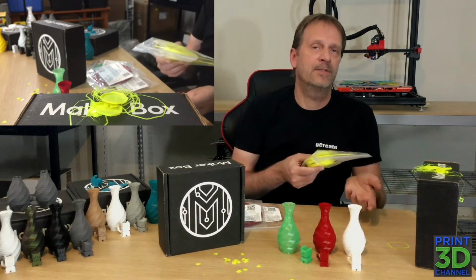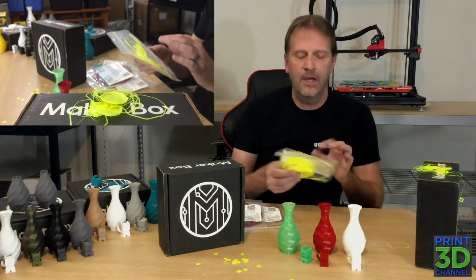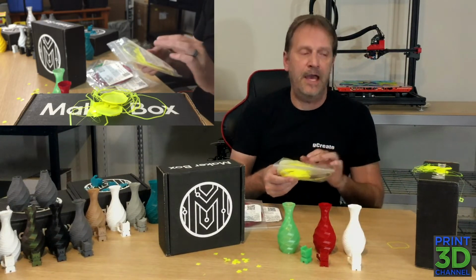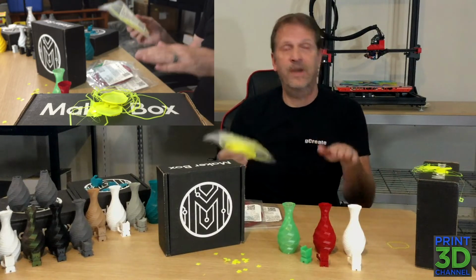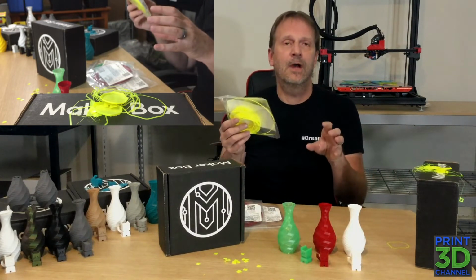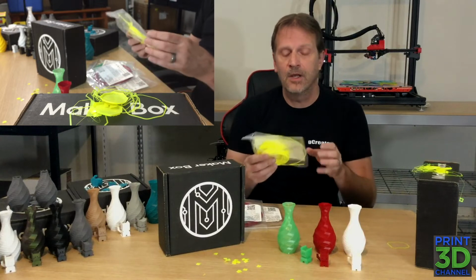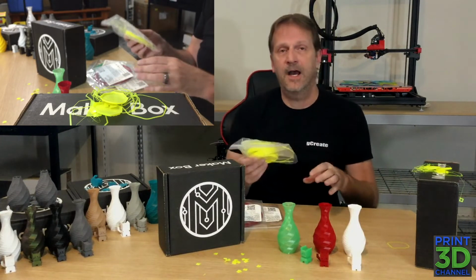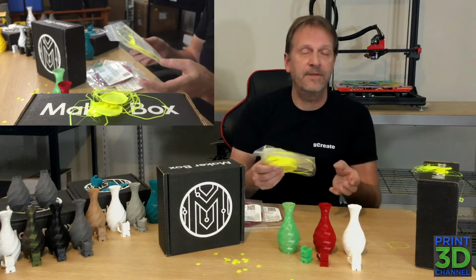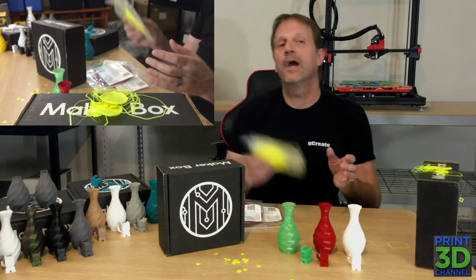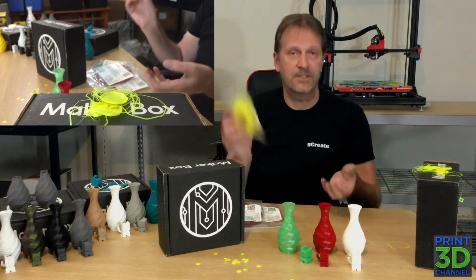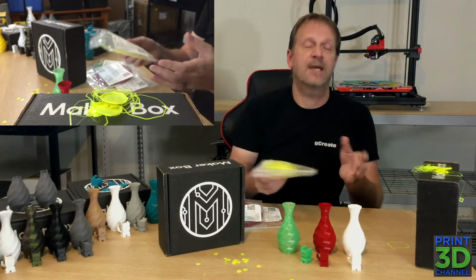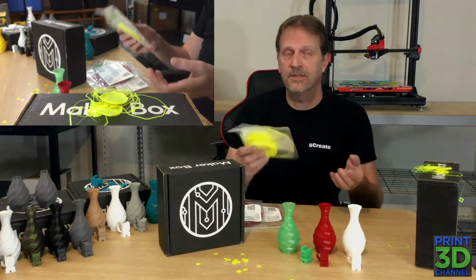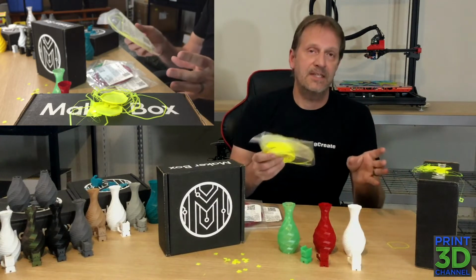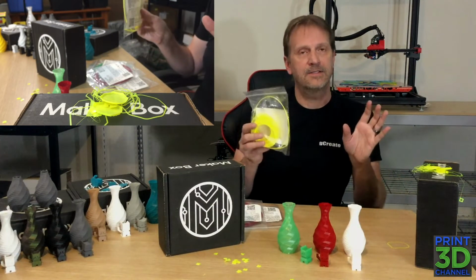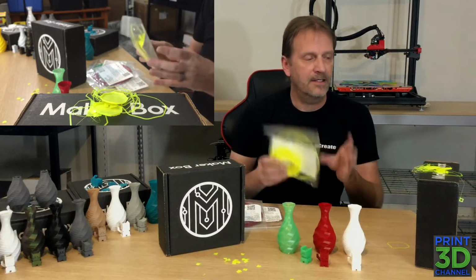If I adjusted the temperature of the bed, turned the bed off, used some Magigoo, I adjusted the temperature in all aspects of the temperature range during all my other testing, leaning towards bed adhesion, which was turning the bed off, turning it on, lowering the temperature below 50 C, which is the recommended temperature, and turning it up over 60 C, which is the high end of the range. And during that time, we did 220, 225, 230, 240, and I actually went up to 260 at one point, and it still would not stay on the bed and continue printing.